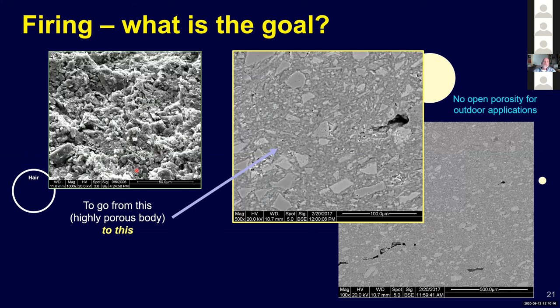And what we want to do is we want to fire in the process to go from this to essentially this middle image, if you will, where you can see the large particles, which are grog, crushed up previously used body usually. And you can see the clay matrix in between there, but you also see that there's very little porosity. There's a hole here, but this hole does not connect to the outside. So that's called a closed pore. And our goal is to have no open porosity. You don't want open porosity where water can get into the body, and then the water, when it freezes, expands by 9%, and then you crack the body. Okay.